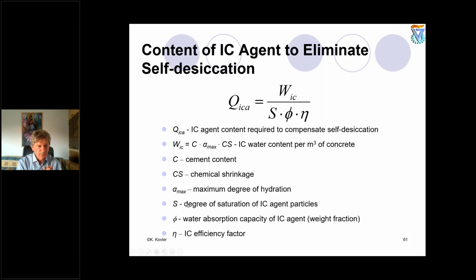And then to have a fully saturated condition in the pumice particle, we need to do something very special. For example, we need to make a vacuum saturation under vacuum, or at least we need to do our best to boil water. When we boil water, we can fully saturate particles within 2-3 days. If we use vacuum saturation, we can do it very quickly. Let's say a fully saturated condition is obtained within half an hour. When we try to saturate by immersing this lightweight aggregate in normal room temperature water, it can take 2-3 months to have a fully saturated condition.